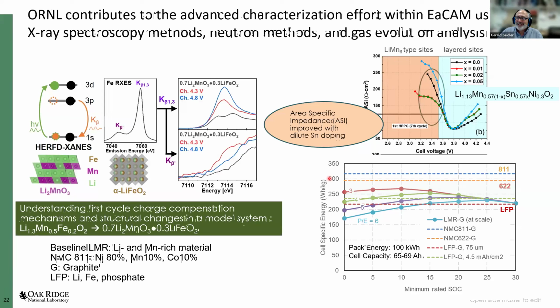Now that you've done it once, do you have a recommended dopant for NMC 811 that will make it perform even better? People put molybdenum dopant, right? And with X-ray absorption, we have shown that the molybdenum stays as 6+. It cannot be electroactive at those voltage ranges. So your suspicion is it's the same idea, it is in the grain boundaries. We are never able to see a metal correlation corresponding to molybdenum in the lattice. Got it. In fact, we wrote a patent on this 15 years ago while I was at Argonne. Very good. All right, we have a last question from Robert Gordon.